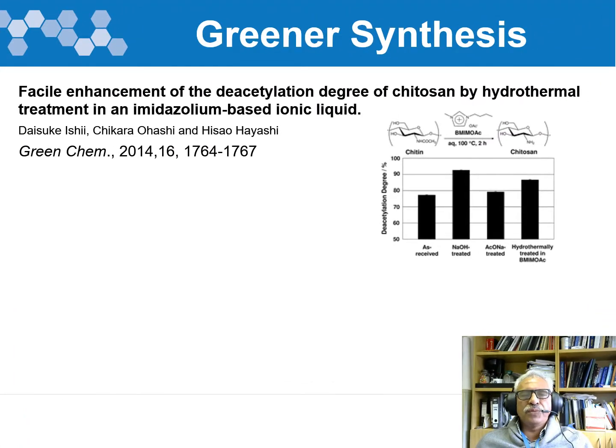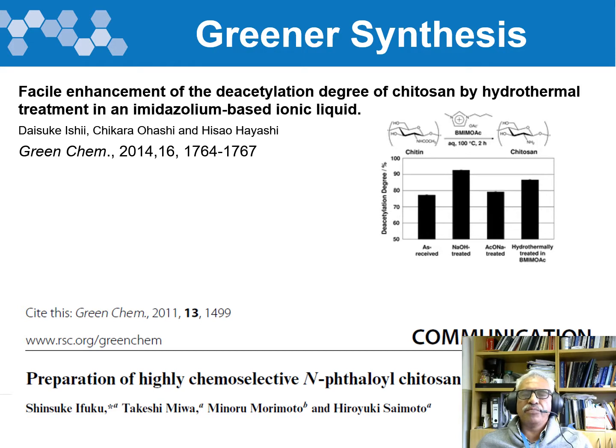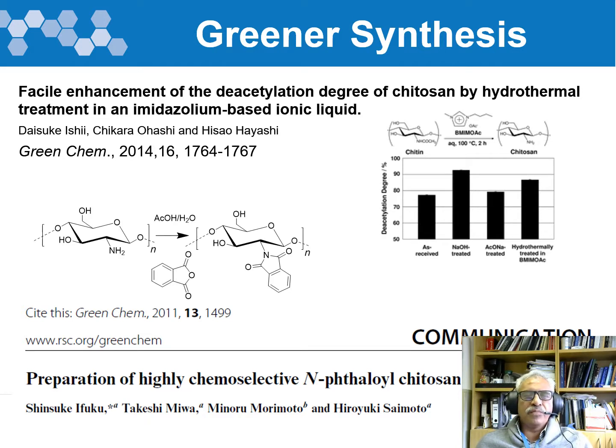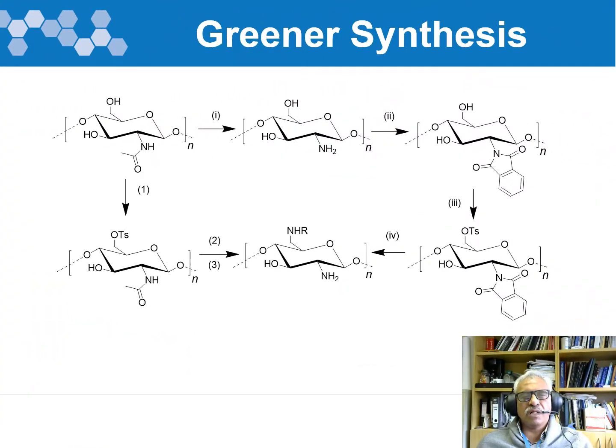So we wanted to follow green synthesis, so there were some ionic liquid mediated protection and deprotection. For chitin and chitosan, instead of using sodium hydroxide, you could use this imidazolium ionic liquid to do that deacetylation. And also these were done in microwave. Then to protect the amino group with phthaloyl, instead of using DMF, we could use acetic acid in water, which is a much more environmentally friendly solvent, to give as good results.